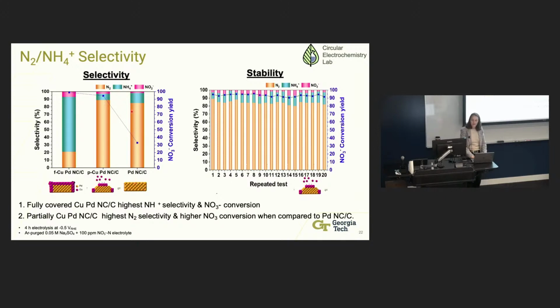And then here, again, this is the palladium. It's a really interesting thing that having palladium, you get mostly nitrogen, a little bit of copper and you still get mostly nitrogen, but then covered in copper, it switches completely from a nitrogen selective process to an ammonia selective process. I'm not showing all of the data, but one thing that we always do is look at the stability over a long period of time. This is an example of the partially covered nanocrystals and the stability. Again, the most important thing here is that it's pretty stable. The orange amount, which is nitrogen, is changing, but not substantially over many cycles.